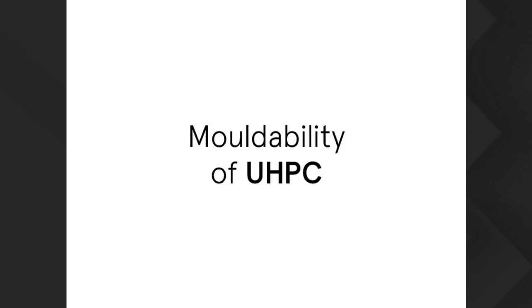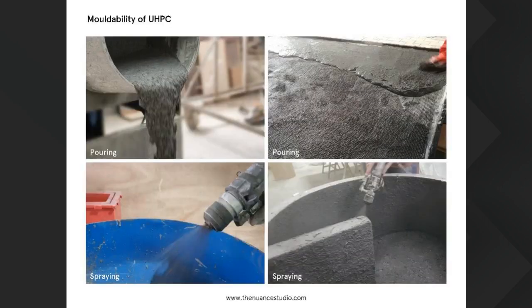A bit about the moldability of UHPC. As I told you, we really don't use metal rods and things like that. Fibers are actually blended into the concrete. This kind of UHPC is generally poured into an open mold. It's like a self-compacting concrete. The other thing is that you could also spray them. You would be able to spray this just the way you're seeing, directly into a mold. We have special machinery, and you'd be able to spray them.